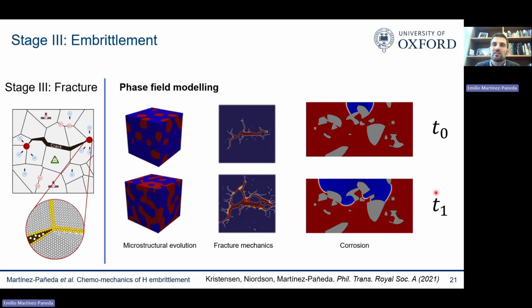I won't have time to discuss corrosion, but we have shown quite recently in my group, and also in a group in Hong Kong and another in the US, that you can use the same phase field idea to simulate the evolution of the corrosion front, to capture material dissolution and corrosion. This is quite important because corrosion is a long-standing, complicated and important problem, and this provides an avenue to simulate this process and predict corrosion failure.